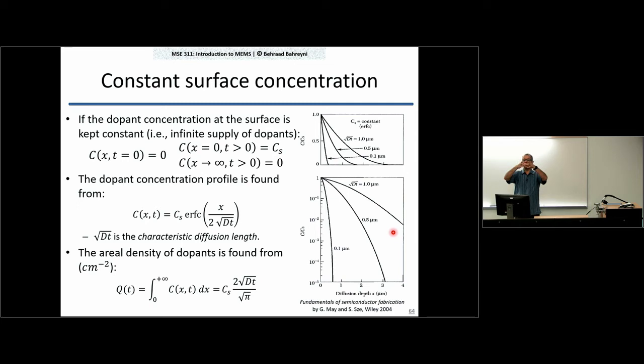And if you look at the areal density, meaning that if you take one square area here and integrate all of the dopants that you have from the surface all the way to infinite depth, that number keeps increasing, right? It is called the areal density of dopants. So basically I look at C of x and t, which, remember, was atoms per centimeter cubed. I integrate it over a given normalized area from the surface x0 to x infinity, and I expect that number to increase with time, right? Because I keep bringing in new dopants that slowly diffuse into the substrate.